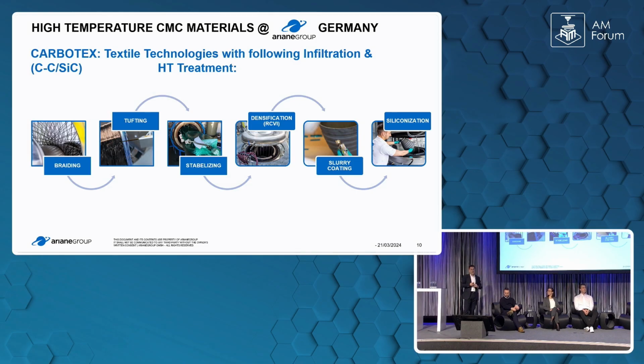There we work on textile technologies, very well known, and we do a 2D structure via braiding, and if we need a reinforcement in the third direction, we do a sewing process, meaning tufting, stabilizing, because then we can do the further ceramization or densification without any tooling. And then, if needed, we do a slurry coating of an environmental barrier coating on the outside or the inside, linked to the application of the part, followed by a siliconization, meaning a high temperature process where you do a conversion of this slurry coating.